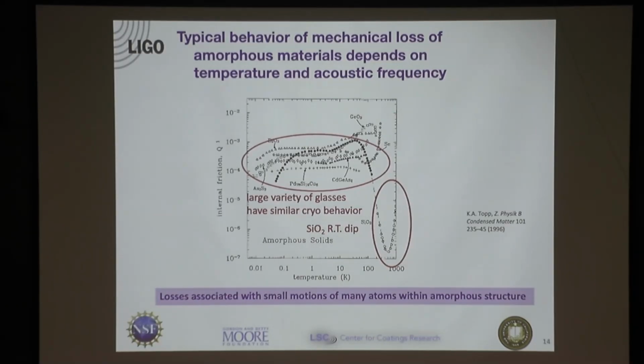And there is a beautiful theory for these, which I will show you in a moment. Actually I will cut quickly to the chase on this because we're running out of time. There is a beautiful theory that explains these modes and why it's a linear heat capacity. There is no theory that explains, or not really, there's some efforts at it, why it's universal. You'll notice an interesting thing, which is silica. The universal range is not supposed to have anything to do with room temperature. This is supposed to be entirely a low temperature tunneling phenomenon. But there is a way in which it empirically also applies at room temperature. There is almost nothing that lies outside that range except silica. Silica has this bizarre thing that it has this enormous dip, and it's deeper than this is even showing. It actually goes down. The better you make it, the deeper it goes.